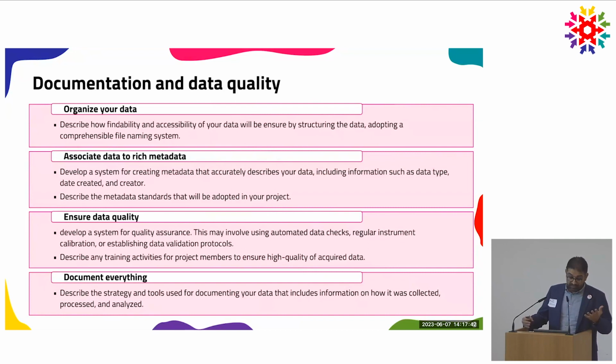The next level is to ensure the data quality and how you're going to manage that in your project. For example, if you are measuring a sample in X-ray photoelectron spectroscopy, manage the frequency of calibrating your instrument with a gold sample, for example, and then the analysis that you're going to do to find the Fermi edge. The same, for example, for Raman spectroscopy, the frequency of using a silicon sample to find the right calibration for the detector. This all has to be described in the DMP.